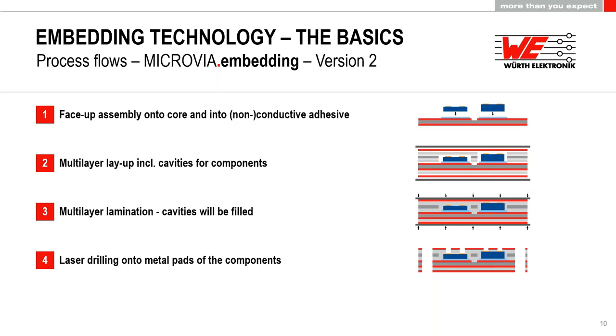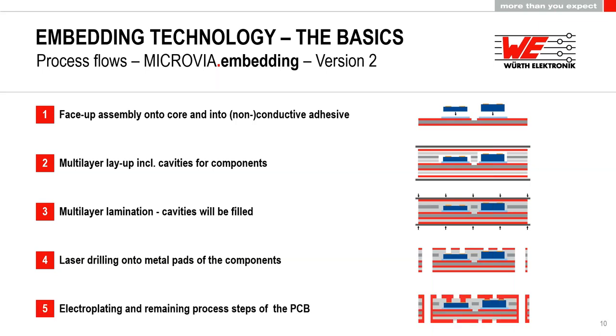And here you might see a little difference between version one and version two. In version two, we have to take care about the height of the components because we are limited in a specific aspect ratio for the microvias. If we have different heights, this would mean we need to have different depths for the microvias as shown in this picture. For the laser drilling, this might not be an issue, but when we come to the electroplating, this will be an issue because in an aspect ratio, we are limited to 1:1 or 1:1.2, something like this. This means that we basically need almost the same height so that we can do a reliable